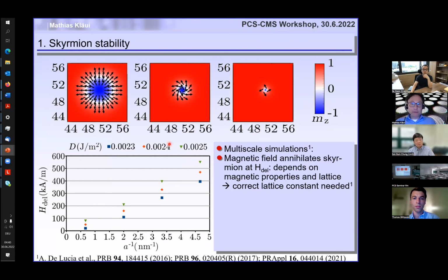As with everything, there is a finite lifetime, but the Skyrmions can be made 40, 50, 60 kBT, so you can make them stable over 100 years if you want to. But there are also very small Skyrmions, which maybe have only energy barriers of a few kBT, which only live milliseconds to seconds. So that depends really on the magnetic properties, the volume, and so on. So you can tune the stability of the Skyrmions from ultra short to ultra long, depending on your application.